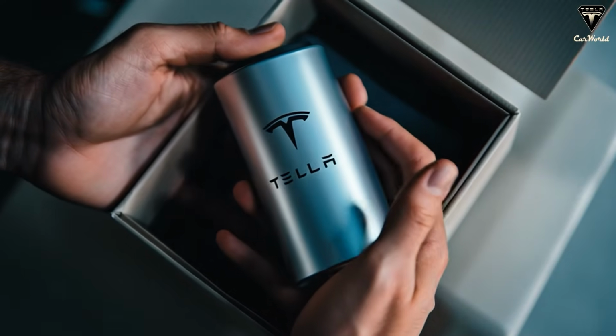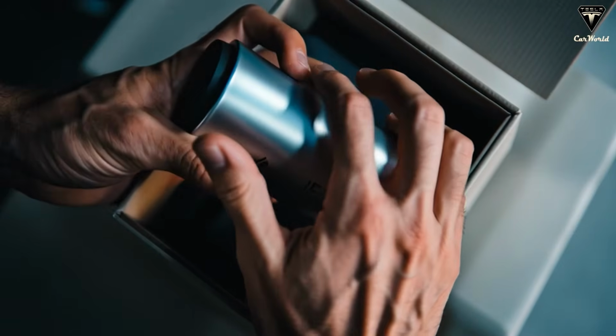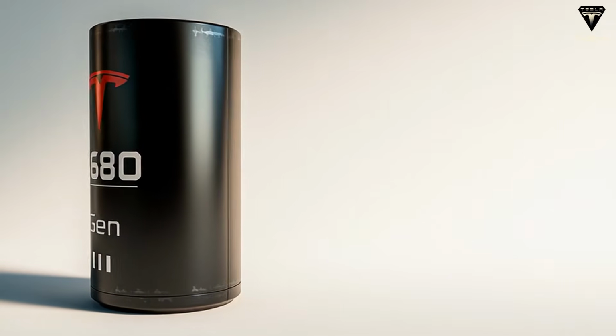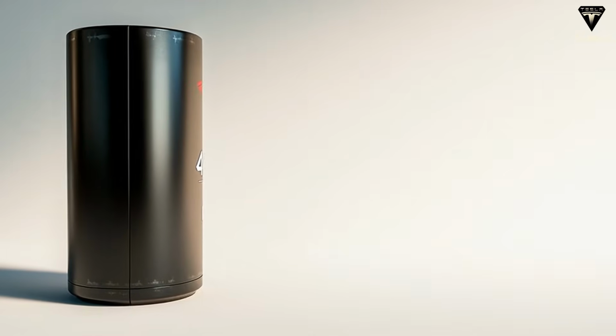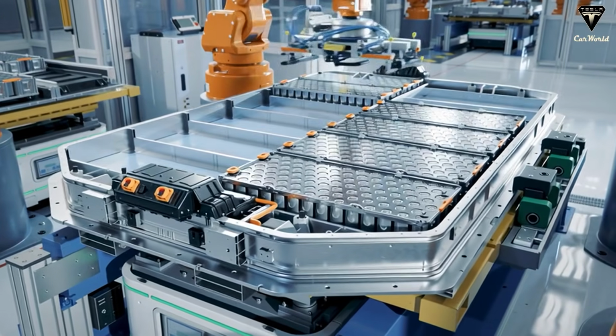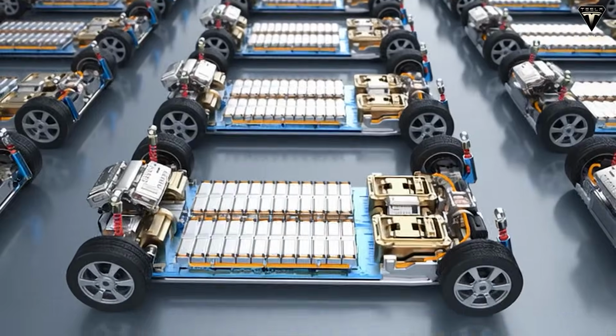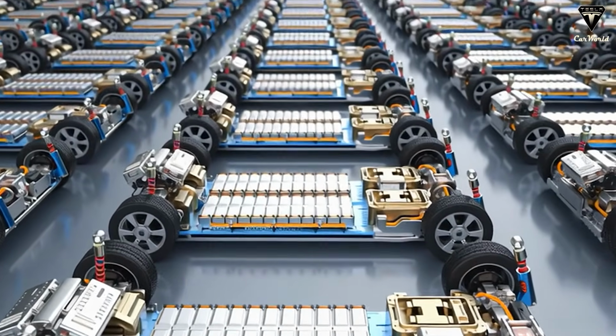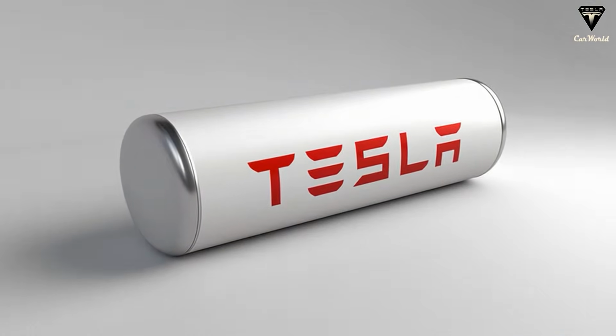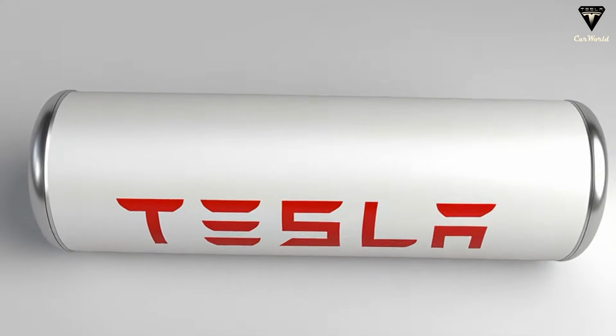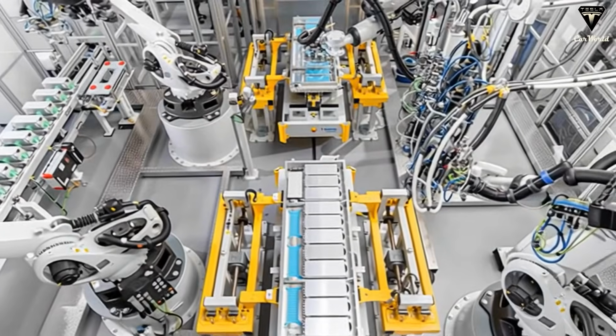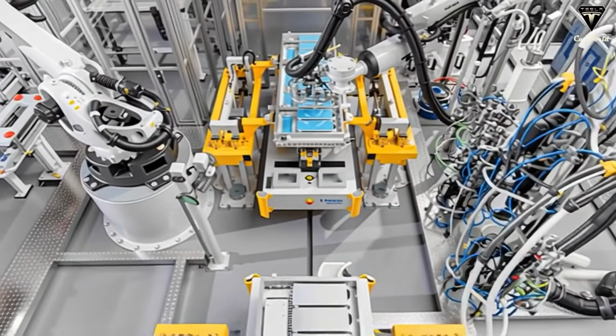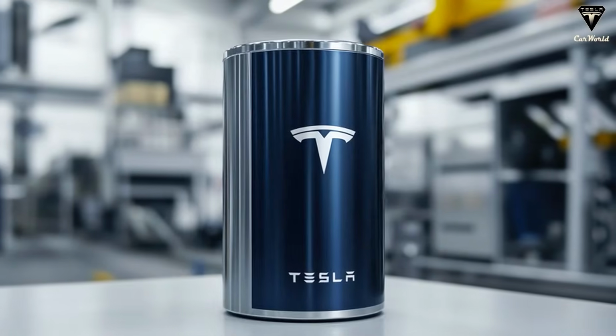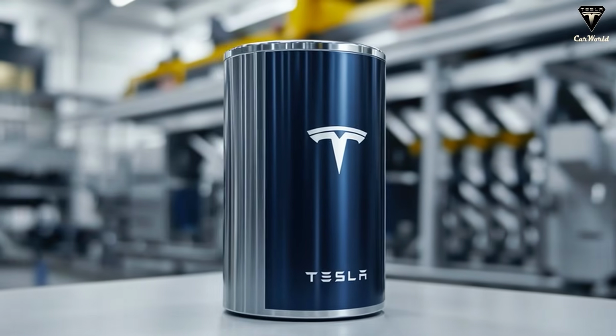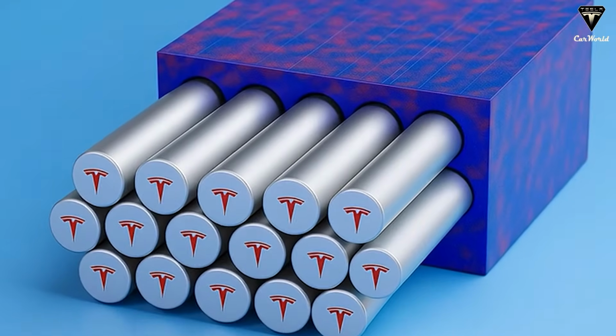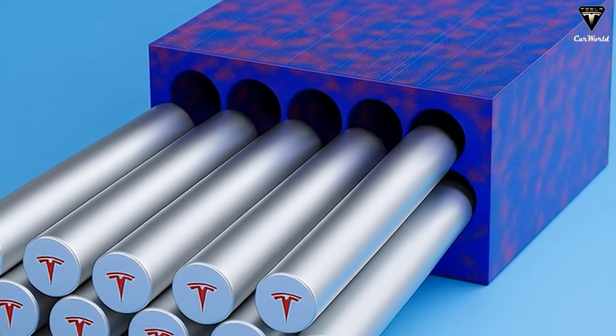For the experiment, a single cell labeled DL2 was placed inside a climate chamber where temperature conditions could be precisely controlled. A 2.4 kilogram steel plate was positioned on top of the battery to apply mechanical pressure during the test. This pressure was relatively small compared with what many solid-state batteries require, suggesting it was mainly used to prevent uneven heating rather than to influence the electrochemical reactions inside the cell. At room temperature, the battery was charged and discharged normally. During this baseline measurement, the cell delivered approximately 24.9 amp-hours of capacity. So far, nothing unusual. But everything changed once the temperature began to rise.